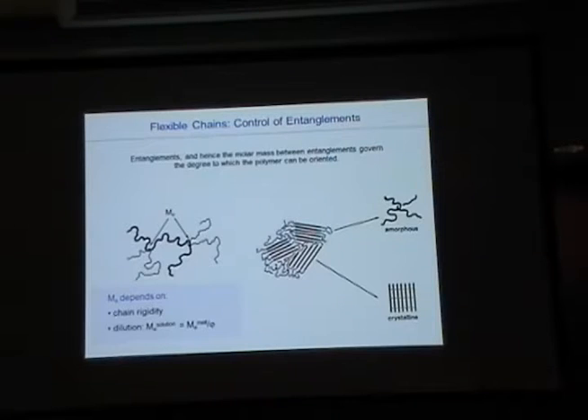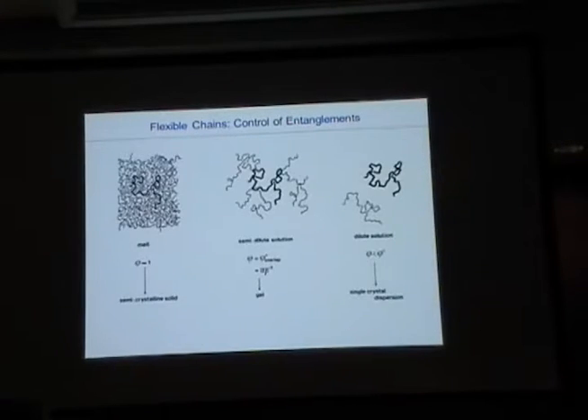Unfortunately, and I will repeat that later on, a lot of our semiconducting polymers are not plastic, meaning that they hardly have enough entanglements because simply they're too short. The molecular weight is smaller than Me, because I have to say Me only depends on the chemistry, on the chemical nature of the chain, nothing else.